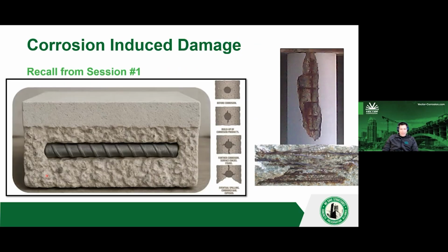The corrosion of the bar itself isn't necessarily the issue. It's more that when steel corrodes, it expands and it puts tensile forces inside of this concrete that we know doesn't like it. And that's when you see the cracking and spalling. Corrosion can affect both conventionally reinforced as well as pre-stressed or post-tension elements. With conventional reinforcing, usually you're going to see these signs of concrete cracking and spalling well before you have a structural issue, so you can go ahead and fix it before it's a problem. On the other hand, with pre-stressed or post-tension elements, you may lose structural capacity well before you get those physical signs of concrete cracking and spalling. Not the presentation for it, but session 2 covered pre-stressing and post-tensioning quite thoroughly. I encourage you to go check that one out.